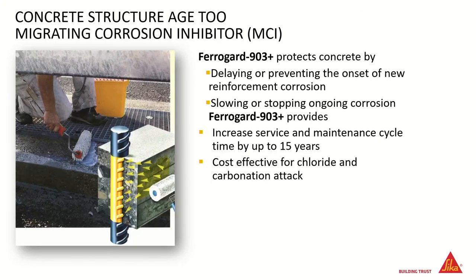For steel reinforced concrete structures, we also have options to try and return if the corrosion has already started or we have a contaminated concrete where there's a higher risk of corrosion initiating, then we can put something like these migrating corrosion inhibitors on the surface. Now these are chemicals designed specifically to penetrate through the concrete until such time that they reach the reinforcement. And when they reach the reinforcement, they react. And that reaction will passivate or create a passive layer around the reinforcement.